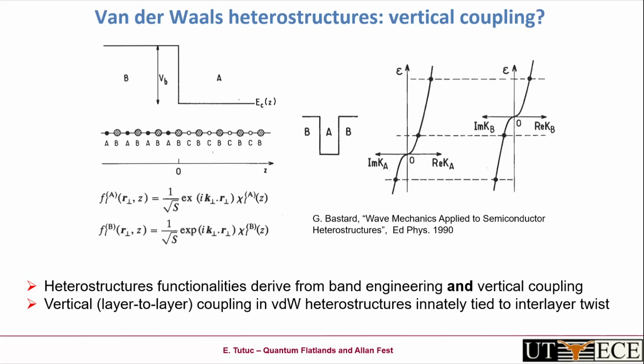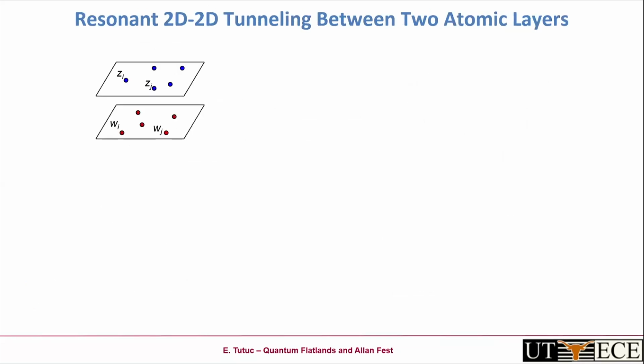That registration gives us, for granted, the fact that the in-plane electron momentum is a good quantum number from one layer to another, okay? If you work on MBE-grown structures, you take that for granted. But if you make heterostructures of 2D materials that are stacked, perhaps without twist control, this assumption basically no longer holds. In-plane momentum is no longer a good quantum number, okay?